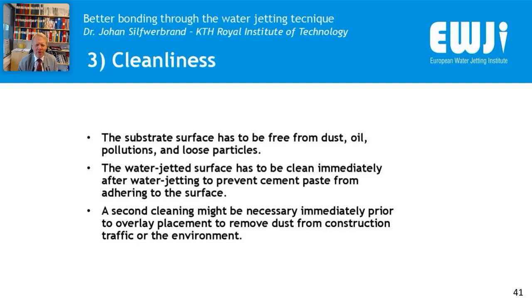It is a combination with the water that you have, or the moisture. And then if it takes some weeks between the water jet operation and the casting of the overlay, you need to make a second cleaning. It might be necessary immediately prior to the overlay placement to remove dust from construction traffic, or if you have a polluted environment.